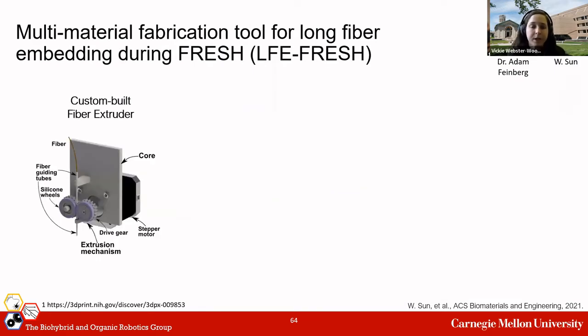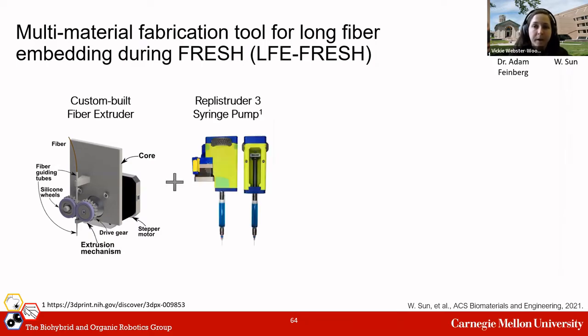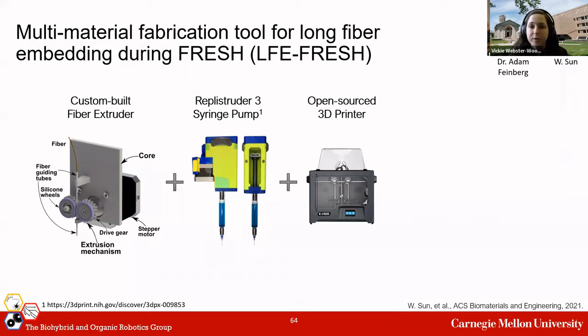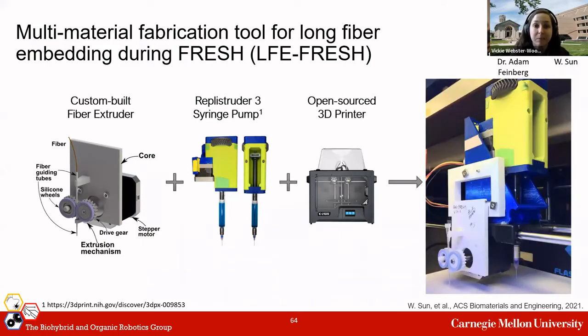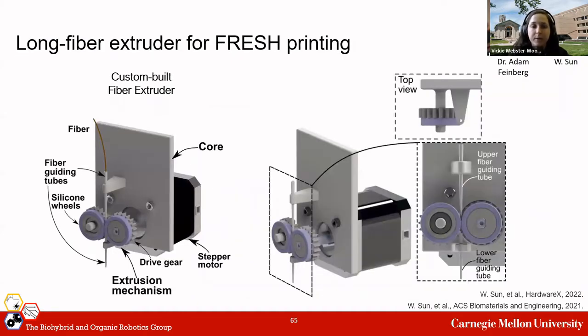To overcome this limitation, we developed a new fiber reinforcing printhead that allows prefabricated fibers to be embedded in the hydrogel during printing. We combine this with a Replistruder 3 syringe pump and an open source 3D printer in order to create a multi-material printing platform. The long fiber extruder is composed of 2 guiding tubes to direct the fiber through a pair of soft silicone driving wheels to allow the fiber to be extruded without damaging the fiber.